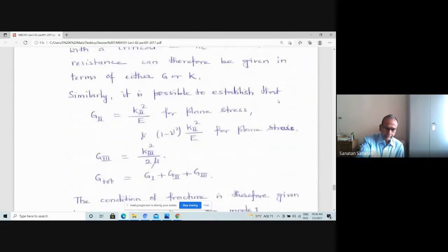So similarly, we also established that G2, the mode 2 strain energy release rate, is related to K2 square by E, where K2 is the mode 2 stress intensity factor, and for mode 3, G3 is the Griffith's energy, and K3, the SIF, is related to the strain energy release rate. So that's how, if somebody says that Griffith's condition is G equal to G critical, then according to Irwin, it is K equal to Kc that is the critical condition. So that's how they became interrelated, and therefore it gave the sound understanding that it is validated from the point of view of energy and also from the point of view of stresses and strains.